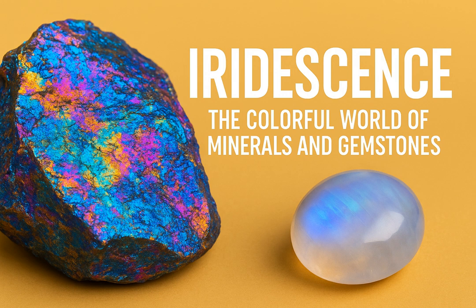Well, yes and no. When we examine the spectral characteristics of Labradorite's iridescence, it's distinctly different from a simple thin film effect, like Newton's rings, which would show alternating dark and bright bands in the spectrum, or only faint first-order colors. How is Labradorite different? Labradorite exhibits a continuous variation of intensity. It often starts with a rich, vibrant blue, far more intense than any faint first-order blue, followed by other rich colors like green and gold as the angle shifts. It doesn't have those simple bands. Why the difference? Why so rich?